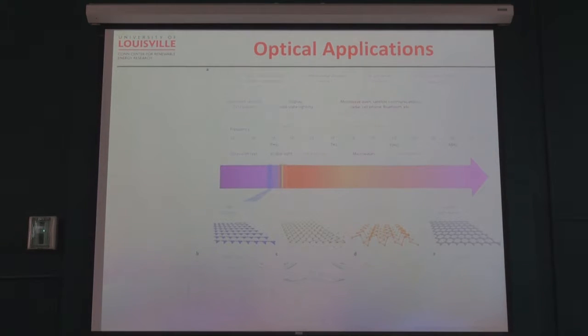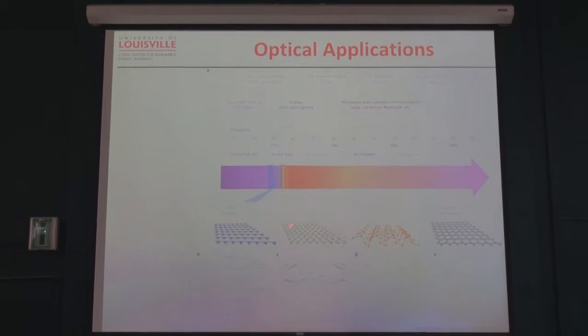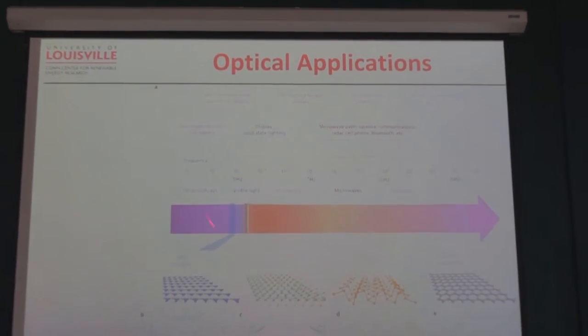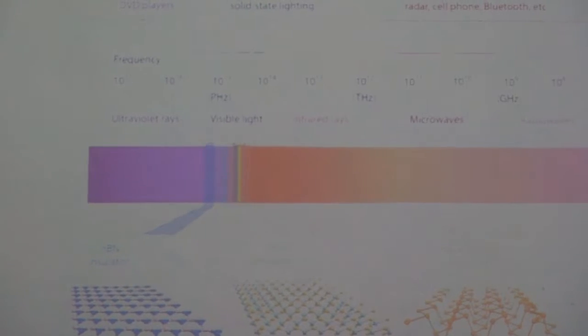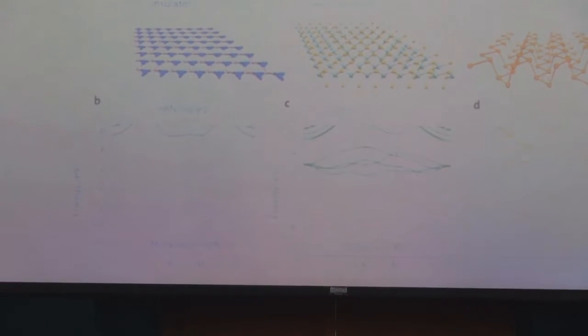So then, depending on these properties, they can have different optical properties. For example, if you take hexagonal boron nitride, its band gap is about 5 electron volts, so it is mostly in the ultraviolet range. If you go to graphene, graphene has almost no band gap, so you can have a small band gap in the infrared range. Then there are other semiconductors with band gaps falling in the visible range, or coming to red or infrared, finally going to microwaves and to much higher frequencies. So depending on your band gap, you can have different optical properties throughout the optical spectrum.